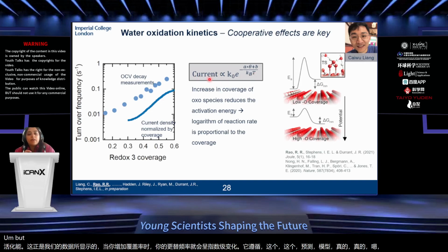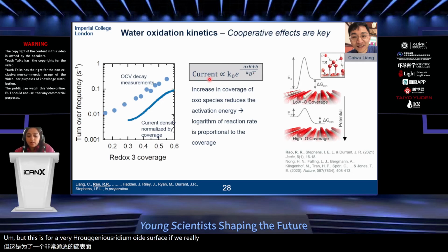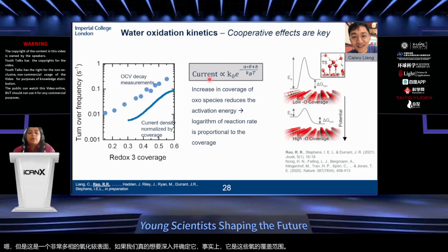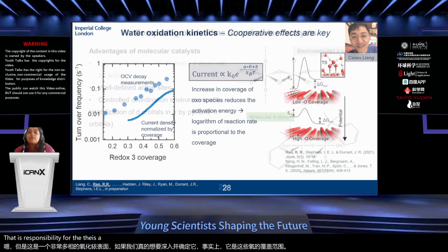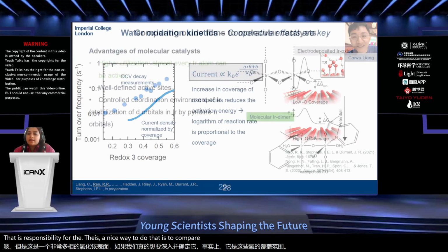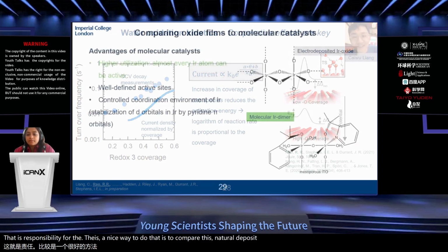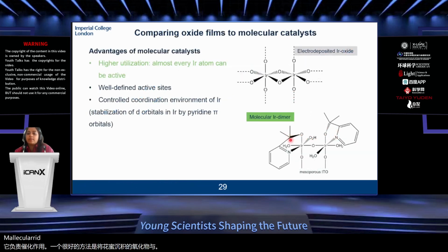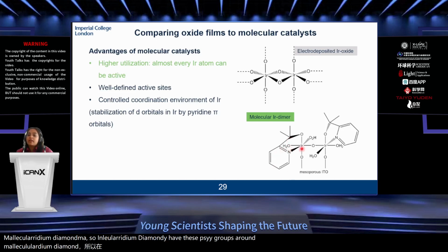But this is for a very heterogeneous iridium oxide surface. If we really want to pinpoint that it is in fact the coverage of these oxo species that is responsible for the catalysis, a nice way to do that is to compare this electrodeposited oxide with molecular iridium dimers. In molecular iridium dimers, you have these cyclic groups around the iridium, and that really impedes this